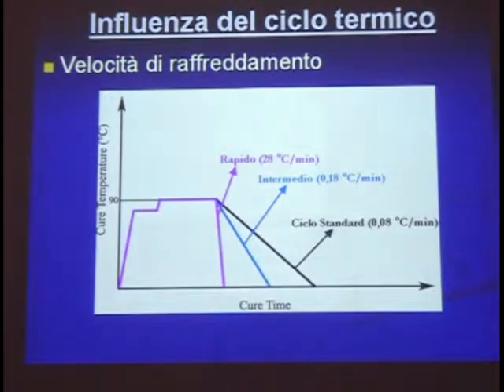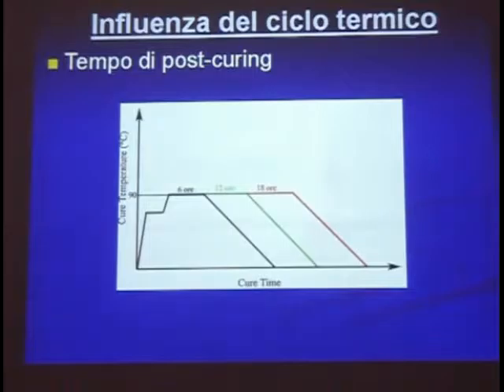Now, this is what we have done with the cooling rate. The standard cycle has a very low cooling rate. We have been trying to accelerate this part so as to save time in the curing cycle. So an intermediate one and a very rapid one, a quenching, which is called rapid, 28 degrees Celsius per minute. So a few minutes. And as for the post-curing time, we have been expanding the standard post-curing time, which is about 6 hours, to 12 hours and 18 hours.